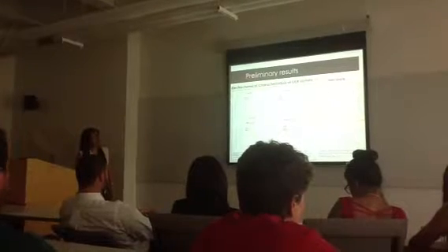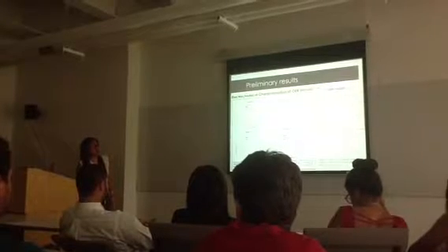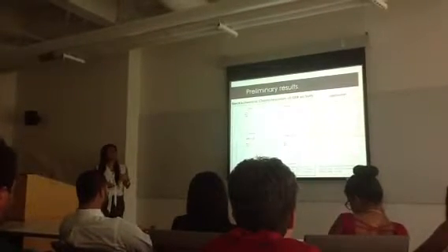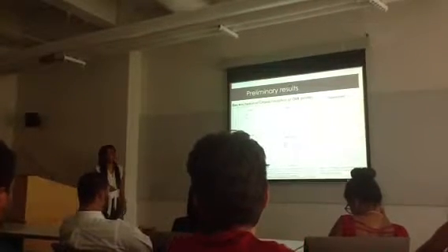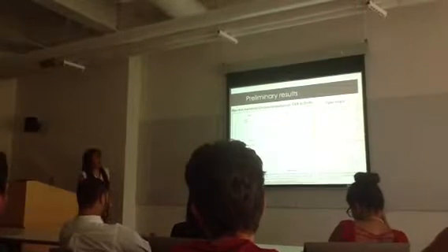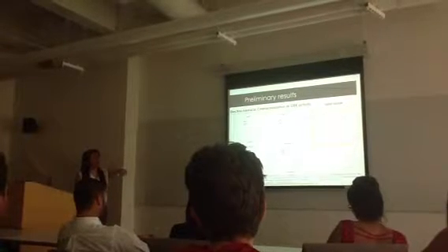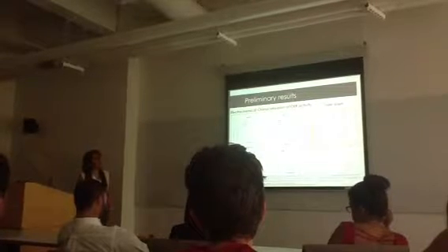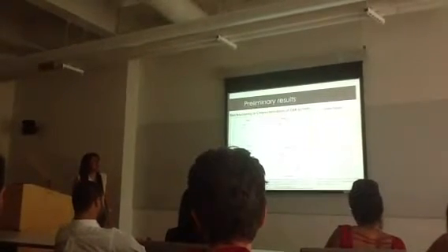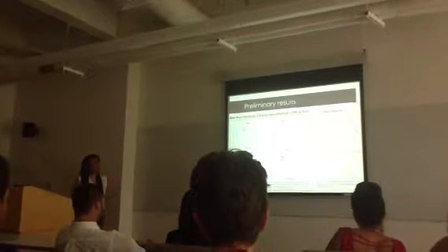And from this type of data, we can obtain the Tafel slope. This is an example of the Tafel slope of this compound, in which we graph the overpotential versus the log of the current density, and we take the slope from here. This is important because we are looking for the smallest possible number, because that means we have to input less overpotential, or less energy, to make the reaction occur. In this table, I do an average of the triplicates of each compound in each cycle, for you to have an idea of the behavior of the Tafel slope. And here you can observe that the 0.7, 0.3 is the one that performs best, because it has the biggest decrease in comparison with these results that, as I mentioned before, achieve the 10% efficiency in the solar water splitting devices.